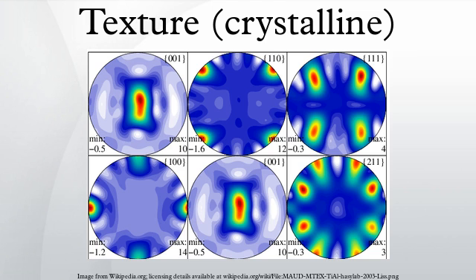Tailoring the texture on demand has become an important task in thin film technology. In the case of oxide compounds intended for transparent conducting films or surface acoustic wave devices, for instance, the polar axis should be aligned along the substrate normal.